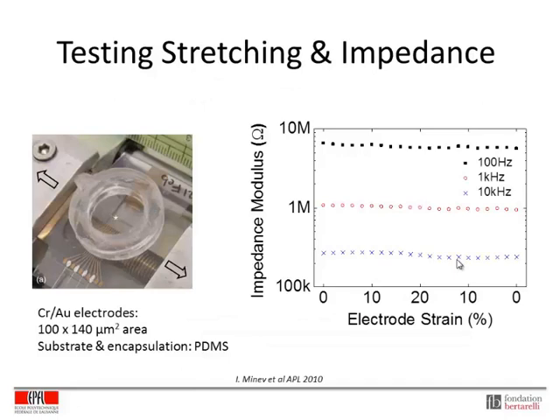So to test the mechanical robustness of our electrodes, we check the behavior of the impedance as a function of stretching and torsion. So on the left, we have an image of the stretching setup that we've used in the past to determine how our electrodes behave with just stretching. So the MEA is placed between two clamps on each side. There is a silicone ring glued on top of the exposed electrodes, and that's where we place our saline for impedance testing.